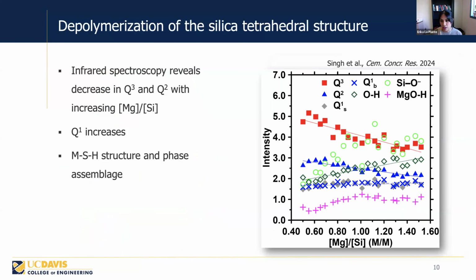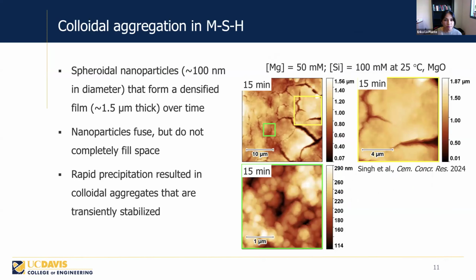So we can now look at a lot more of these curves for different magnesium silicon ratios, and look at their intensities and the different peaks. What we can see here is that there is a decrease in the Q3 and Q2 and an increase in Q1 with increasing magnesium to silicon ratio. So what this shows us is there's depolymerization of the silicate tetrahedral structure as we increase the magnesium silicon ratio, and also shows us the phase assemblage and the structure of the phase as we're changing the solution composition.